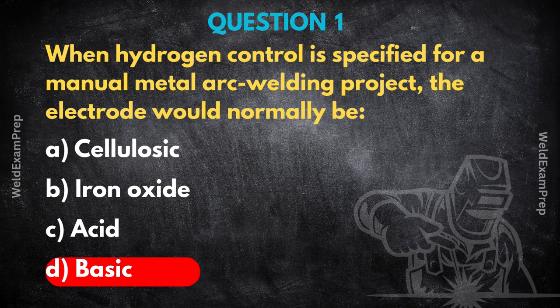So an inspector can sign off on a weld that looks completely perfect, and then hours later, catastrophic failure could be starting from the inside out. That's it, exactly. And high-strength steels, the kind you see in pressure vessels or offshore structures, they're just much less tolerant to this trapped hydrogen. If you have hydrogen and you have stress, the steel's internal bonds just get weakened and start to pull apart. I know that cellulosic electrodes, option A, they're often faster, great for deep penetration, but they're also notorious for generating a ton of hydrogen. A huge amount.